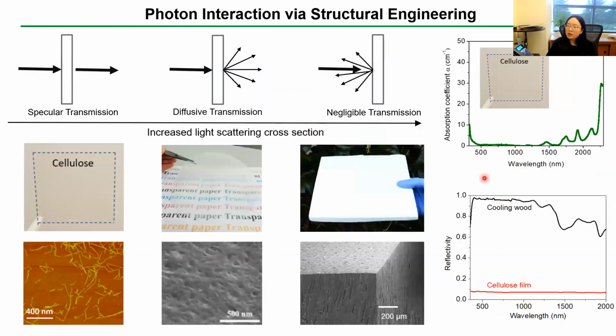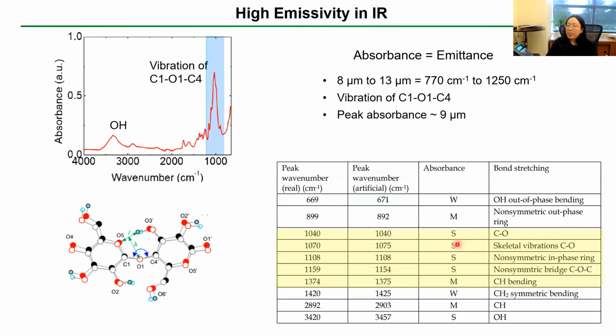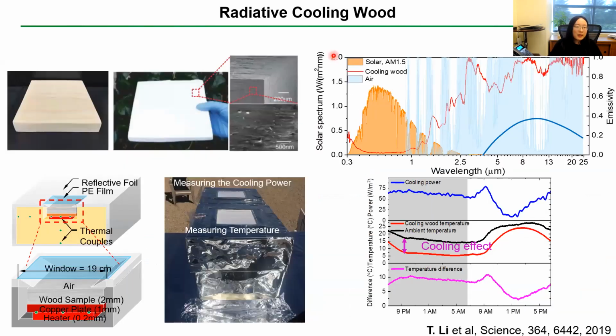We're also trying to preserve the mesoporous structure of wood, because when the pore size is around the micron range, it can effectively backscatter the incoming light. We are also looking at the infrared emission of wood by FTIR measurements. Due to the molecular stretching and vibration, there's very intense emission around 9 micron, which coincidentally lies within the atmospheric transparency window.